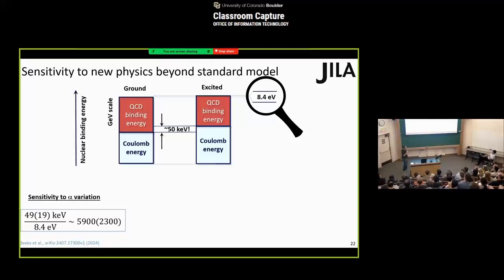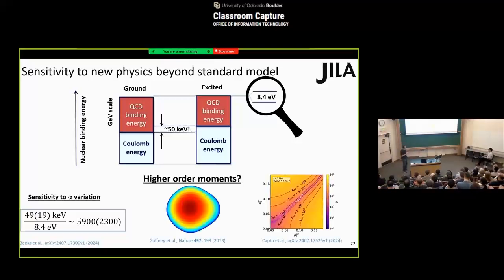Now this is only evaluated with a pure geometrical model up to the quadrupole moment. Of course, there could be even higher order moments present in this large nucleus, which we still don't know about. For example, if there's an octupole moment, it might deform the nucleus in a different way. And there are theoretical investigations on how these high order moments may still change the sensitivity to alpha variations.